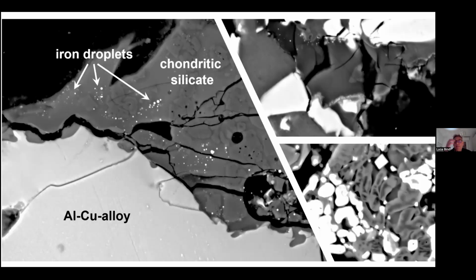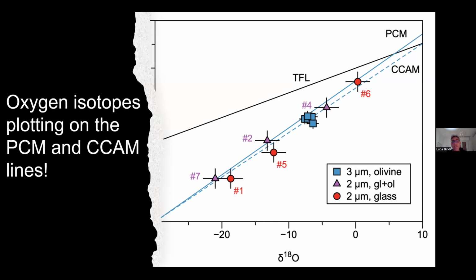I would like to show you some examples, and you can see at the contact, which is actually pretty impressive, you have copper aluminum alloys, chondritic silicate, and again, look at the iron droplets at the border, at the interface. These droplets are due to the reduction of iron in the silicate due to the presence of strong reducing conditions induced by the presence of metallic aluminum. Consequently, you have an oxidation of portions of the aluminum in the alloy to form a new generation of spinel and corundum. So this is a very important point, what happens at the interface of the two different systems. And again, look at the oxygen isotopes of the CAI material. Again, they plot perfectly on the CCAM line.